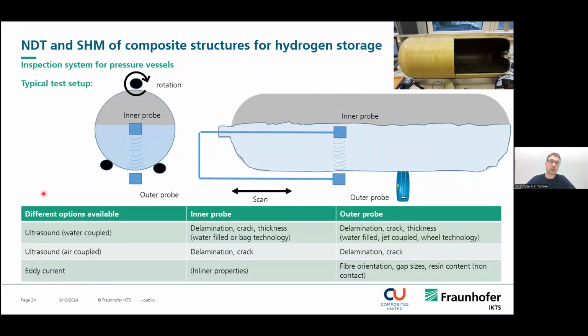So how does it work? We can combine different probes. That means also different possibilities to detect defects. We can work with an inner probe and an outer probe. This outer probe can be this roll, as you've seen in the picture on the previous slide. And by using different techniques for the coupling, for example, water coupling, and in this figure, of course, the vessel is filled with water, but you can also work only with a really thin film on this roll. Or you can also use ultrasound which is only air coupled. By using this, you can detect different defects, for example, after manufacturing of such a pressure vessel. Defects could be delaminations, cracks, or changes in the thickness. And also, as you've seen, by combining different inspection methods, including eddy current, you can also measure the fiber orientation, gap sizes, or the resin content in your component.